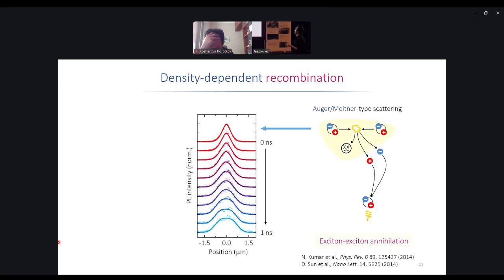And the consequence of this annihilation is relatively straightforward. If you have a distribution of particles and you have density-dependent nonlinear recombination, so the more particles you have, the more they annihilate, then what will happen is, as you see here, in the middle when the density is high, the density will decrease faster than on the flanks. Yeah? So your Gaussian distribution will morph into something like a flat top without anything diffusing. Yeah? So the shape of your distribution will change over time, and that will give an effectively measured increase of diffusivity without actually meaning that the transport is, in fact, faster. Just because the shape changes, so the distribution becomes broader because of this effect.